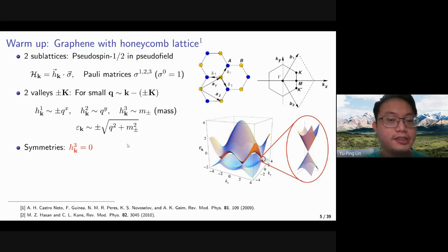And we can understand it further by considering the symmetry of graphene, and it will turn out that the third component should vanish. So first, let us look at the inversion symmetry. By inversion, we can think of it as reversing A and B sublattice sides. It means that in terms of the Hamiltonian, we can think of it as a unitary transformation with the off-diagonal sigma 1. And under inversion, we are mapping k to negative k, so the Hamiltonians are related. And under inversion, it is required that the third component has an opposite sign between k and minus k.